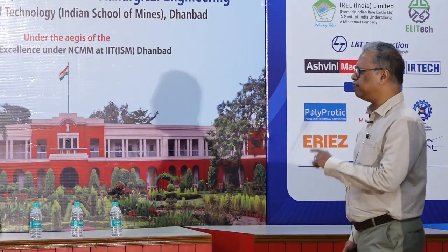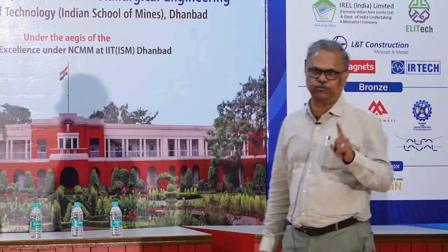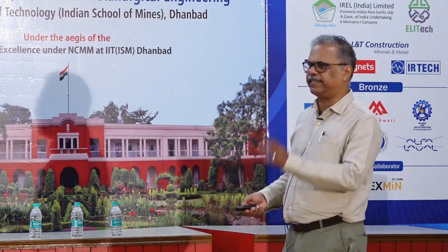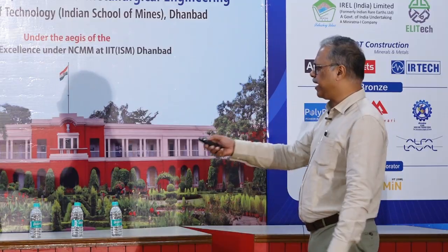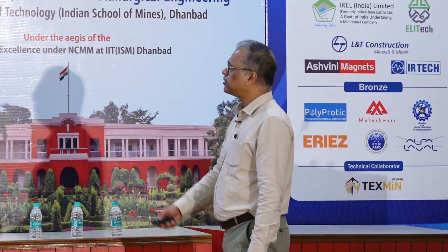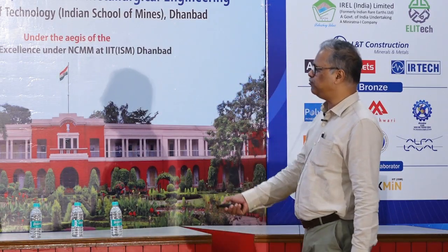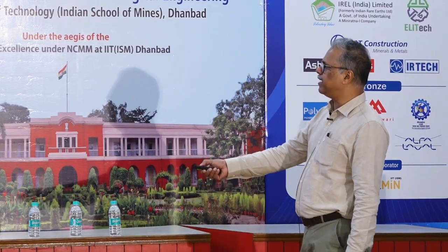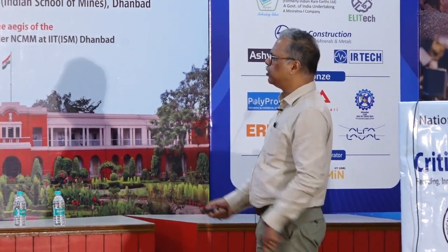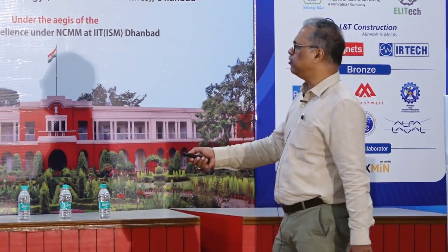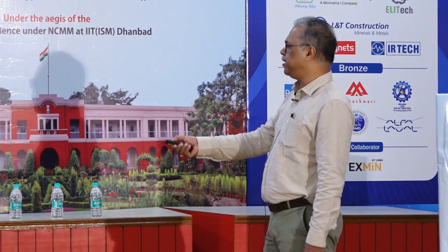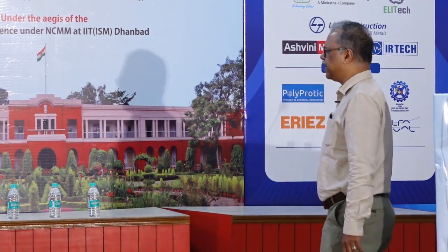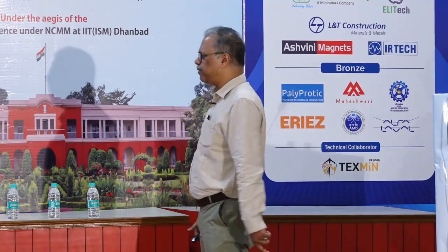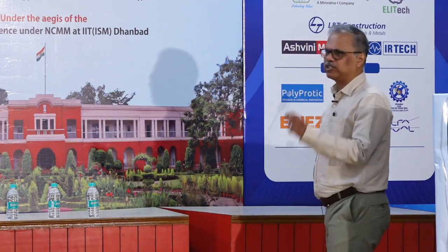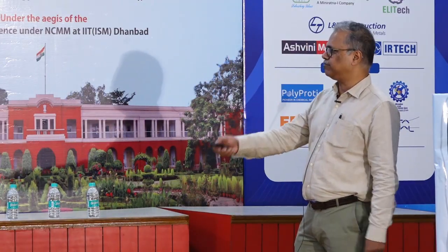This is because grain alignment requires a certain level of anisotropic grain growth. That has to be there, and that's why hot deformation helps us get those properties of the materials. So in summary, if we can reduce the grain size, then the coercivity and all these things can increase. This is a laboratory scale development, not conventional or commercialized. But applying grain boundary engineering techniques, such as the grain boundary diffusion process, to hot deformed magnets can lead to higher coercivity with a small addition of rare earth elements.